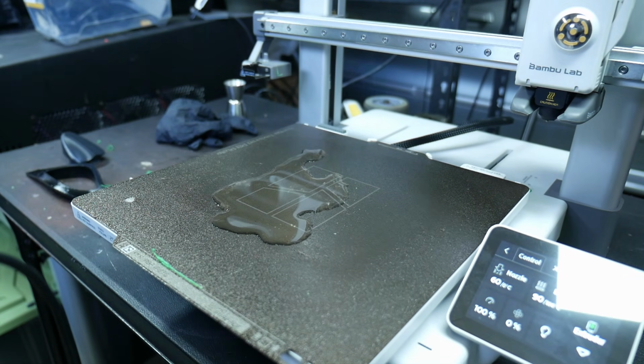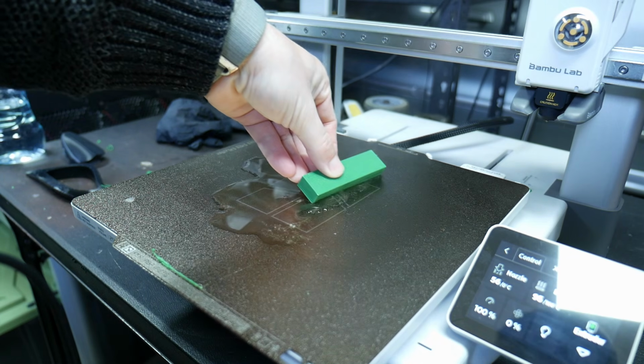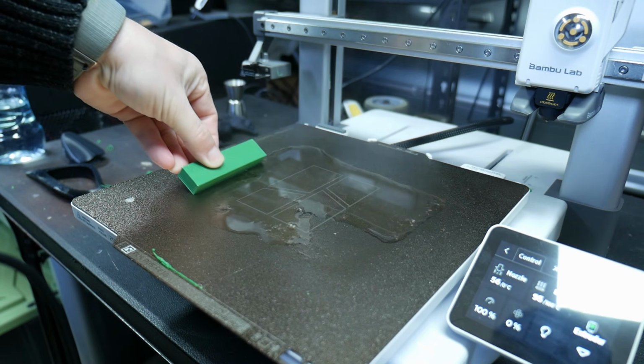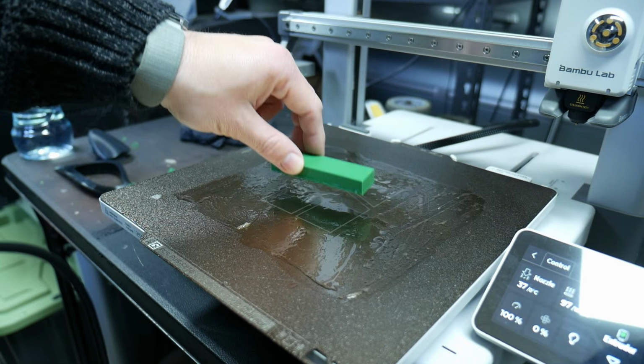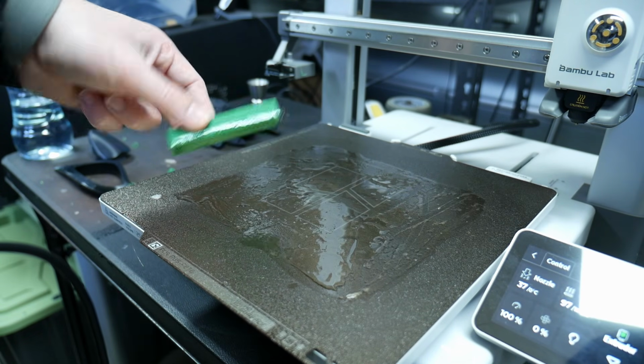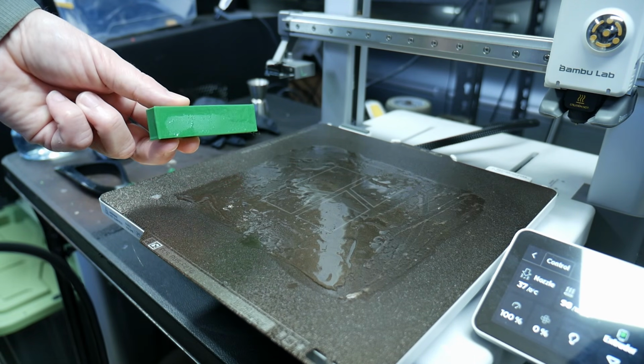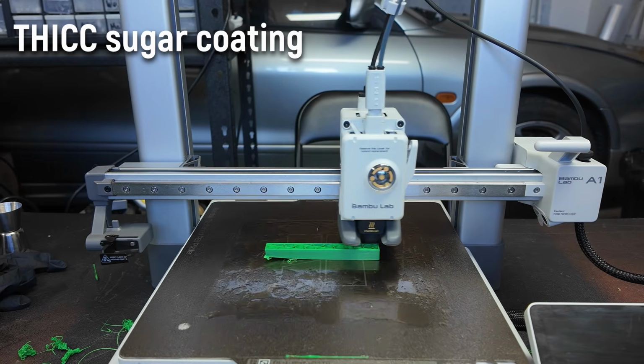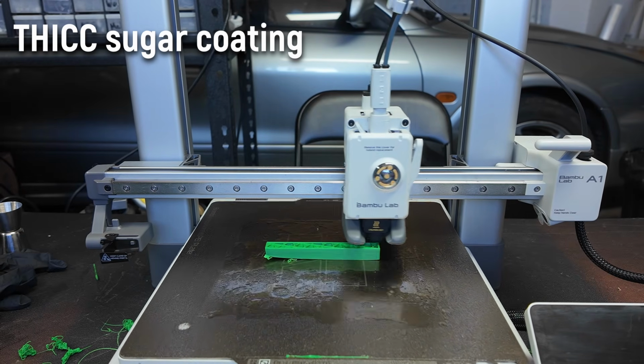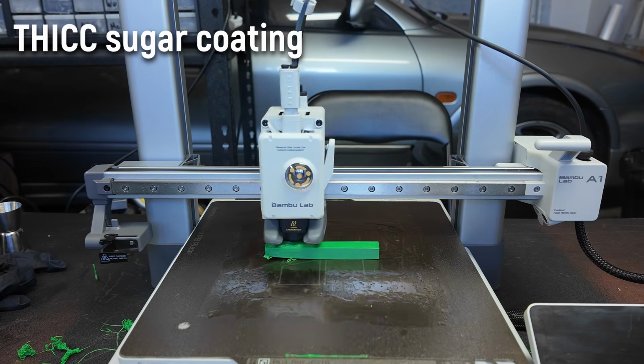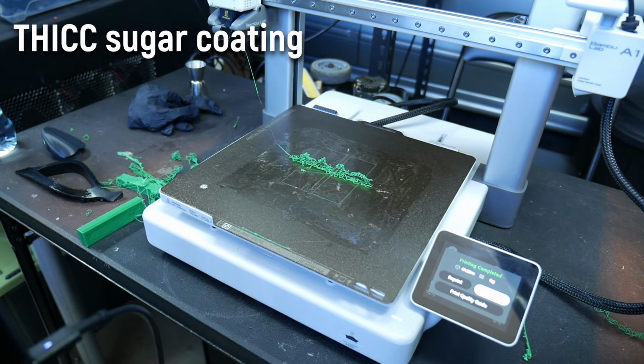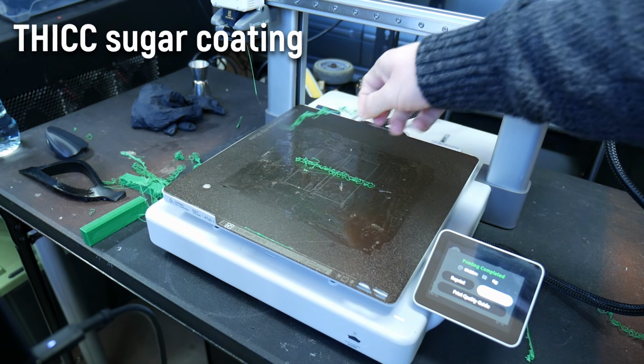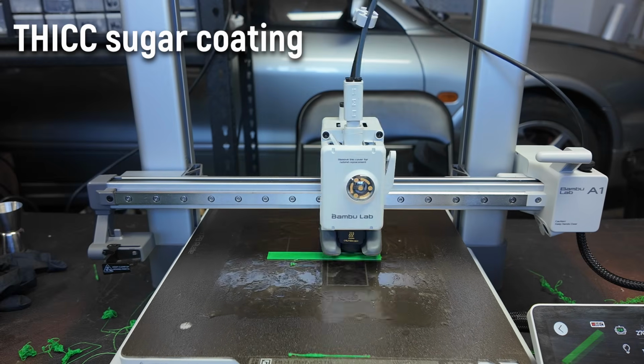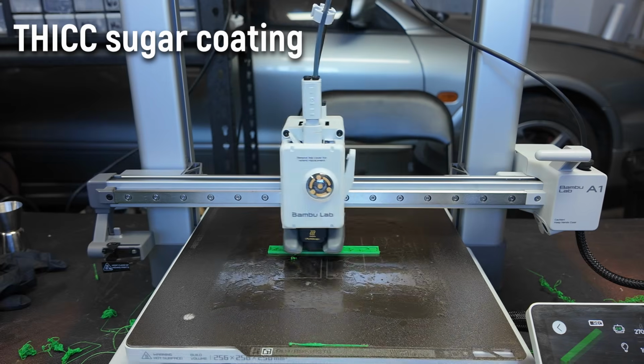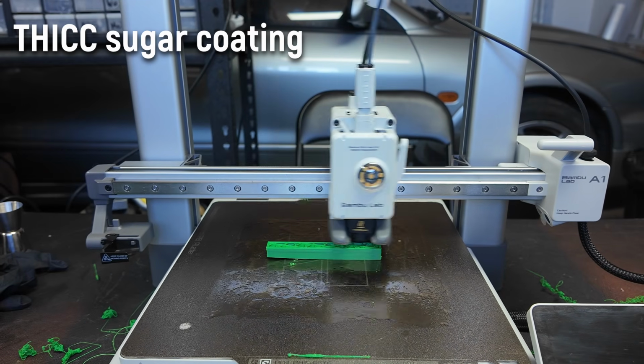So I wiped it all off, started fresh, and in desperation, I carefully poured the sugar solution onto the print bed and heated it to 100 degrees Celsius to see just how much of a sugary coating I could get onto it. As it turns out, quite a lot. Basically, I was making toffee with a 3D printer. And this thick, sticky mess was way too much. The prints were actually getting worse. So maybe there was a sweet spot between too thin and too thick. Pun absolutely intended.